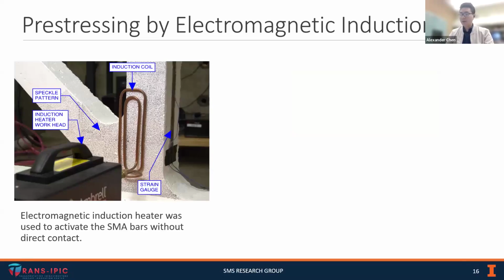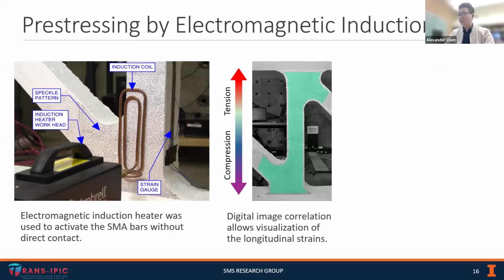Over here is an image of what that setup looks like. You can see we have the induction coil placed up against the specimen that contains the SMA bars. Once we turned on the coil, it began to heat up the SMA bars inside the concrete without direct contact. You also notice that we have a series of dots on the surface of the concrete, and this was so we can use digital image correlation software to track the longitudinal strains.